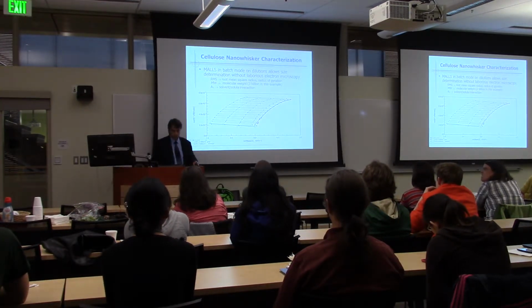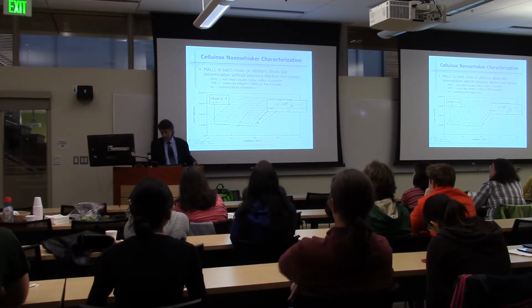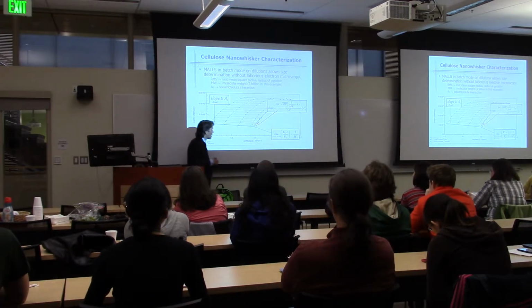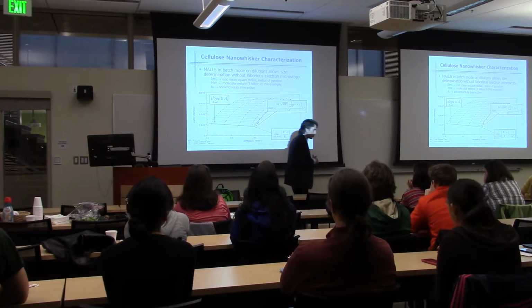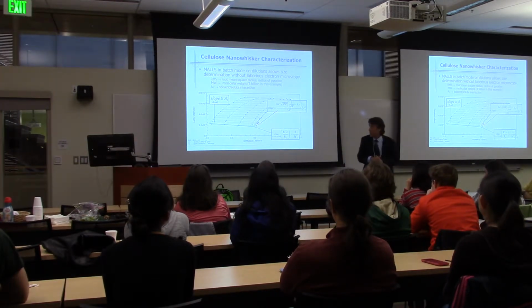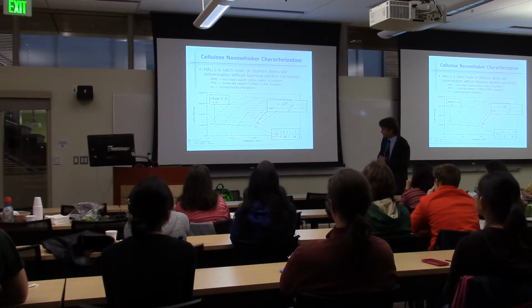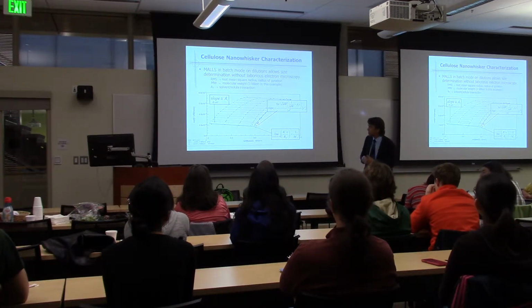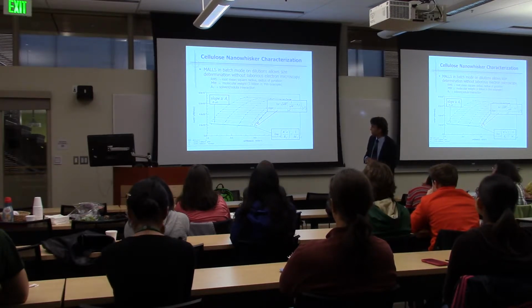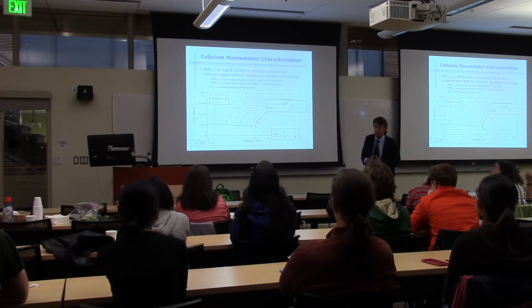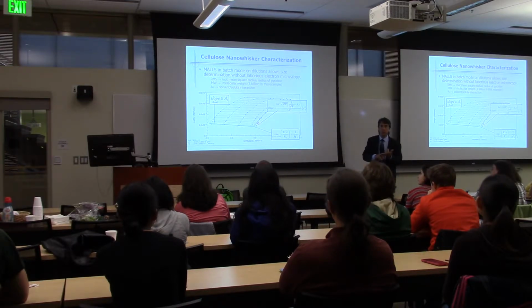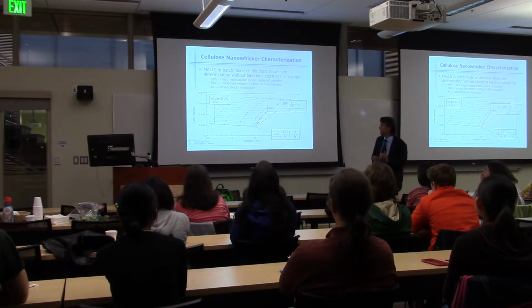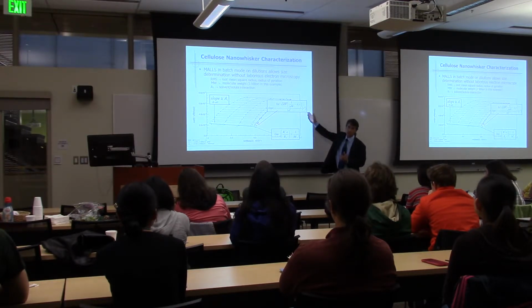And so what we turn to, to do that, is light scattering, and this is multiple angle laser light scattering, a very common tool for polymer scientists. But if you're not familiar with it, it gives you a lot of information. So we're looking really at the scattering at a bunch of different concentrations here as a function of the angle. And there's really three pieces of information that come out of there. One has to do with the thermodynamics, the interaction of the dissolved material with the solvent. The other is a measurement of the absolute molecular weight, the weight average molecular weight. And the final part has to do with the radius of gyration of the material.